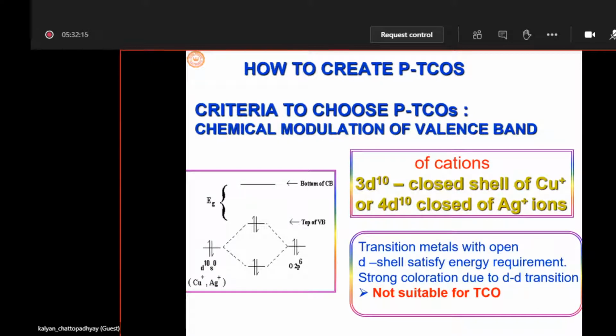And it is found that the copper 3d orbital or silver 4d orbital match this criteria. So you can alloy the orbital of oxygen p with copper 3d or silver 4d to get a compound of suitable nature. Some people suggest that transition metals like iron also have some orbital with energy similar to that of oxygen p.